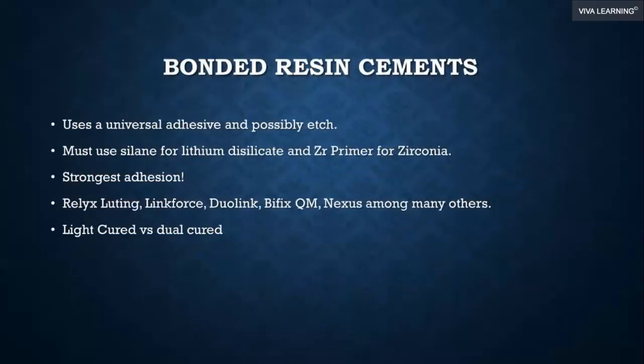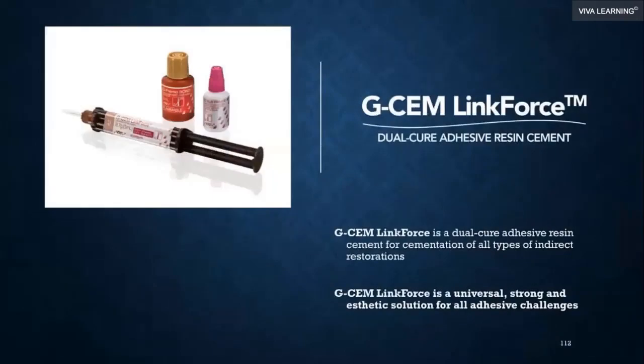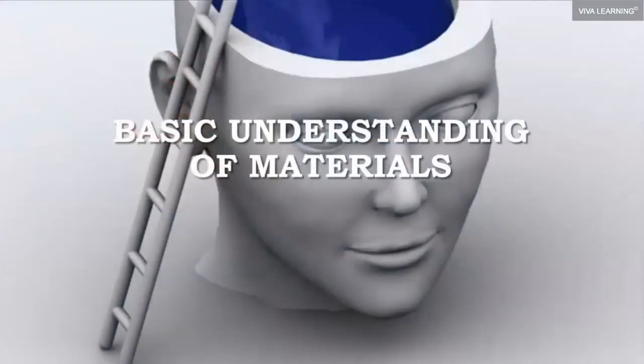Finally, if you want maximum adhesion, you have to bond the crown in, literally bond it in. That means using GC's Premio Bond and what I would call a bonded resin cement, a dual cure resin cement, which will give you the optimal adhesion. The nice part about the Link Force kit is everything comes in there. You can get an entire kit with everything in it, and that's going to give you your optimal adhesion. You have to have this kind of understanding of the materials, because if you understand your materials, then you really know exactly what you're getting in the long run.